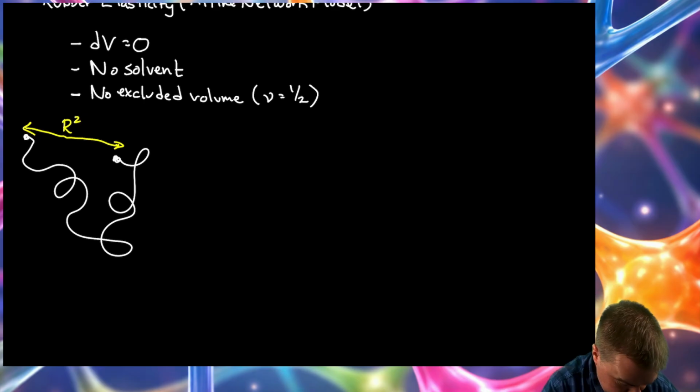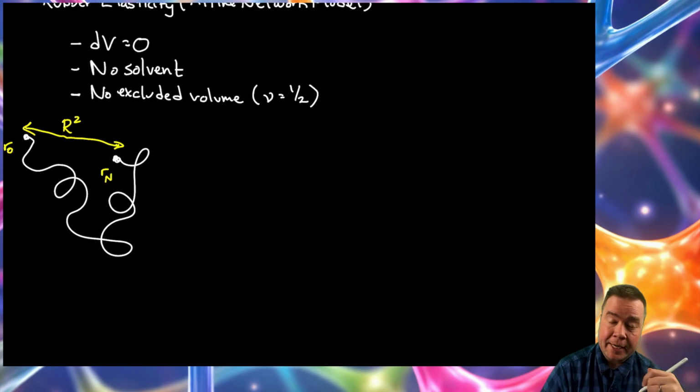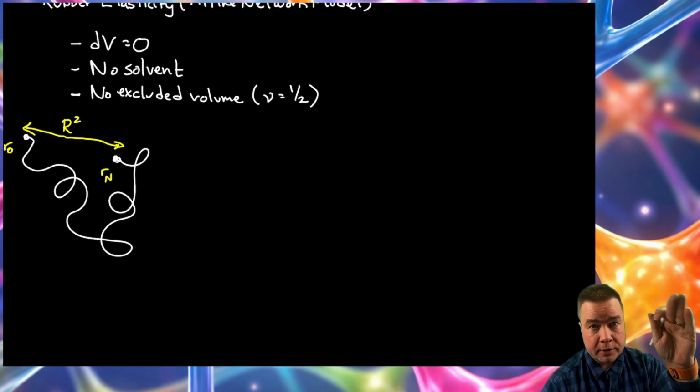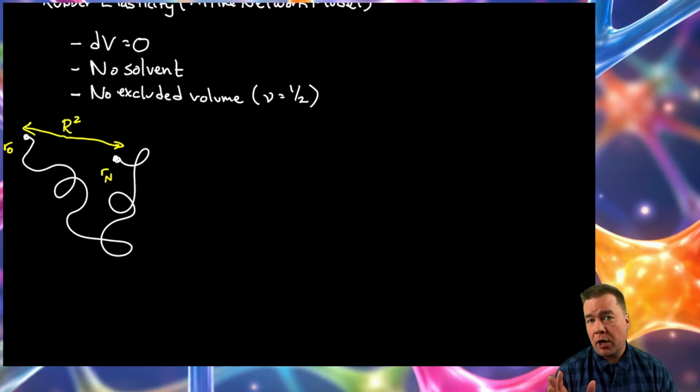And the way to do it is you think back to when we described the ideal chain model, the Gaussian chain model. What we're really asking ourselves is what is the size of the chain as a result of this random walk that occurs as monomers take on different positions, and we've got different bond angles between the segments as we build up the chain from a position R0 all the way to its endpoint, which is R sub n.